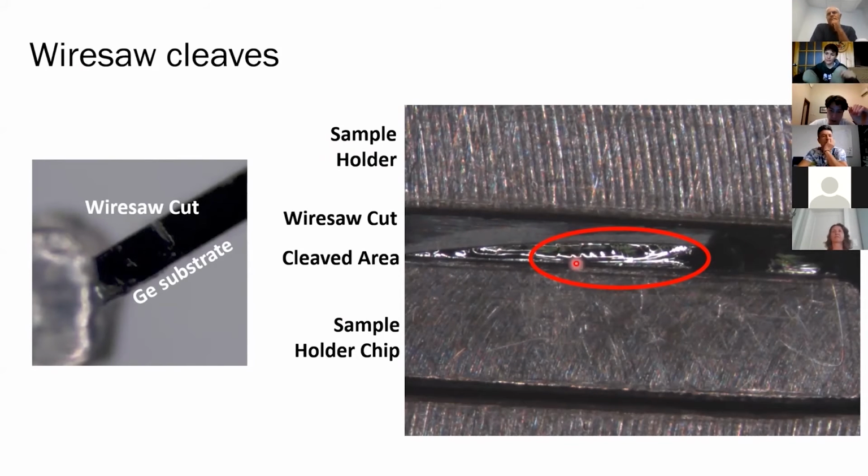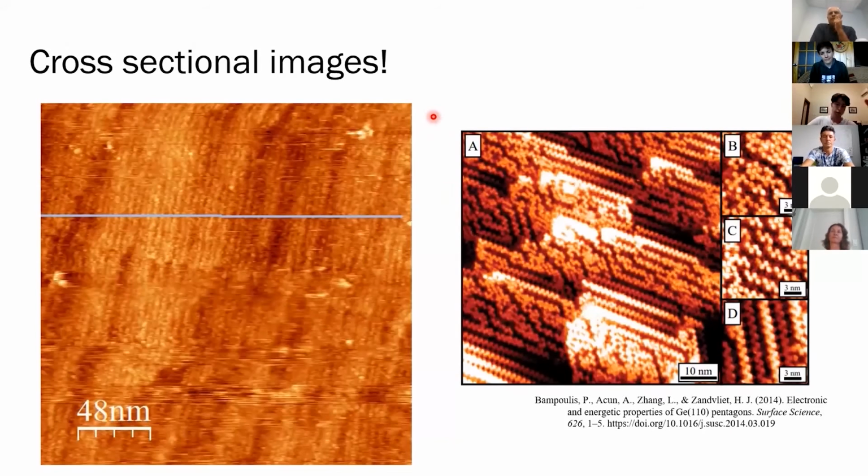there are these terraces almost, these steps, which is encouraging because if there are steps, it most likely points towards flat surfaces in between the steps. Now we don't know what it looks like atomically just from an optical picture, but we can hope that on the atomic scale, it cleaved somewhat similarly to how it cleaved under a microscope. We can also see at the edge maybe some steps and terraces, which is definitely encouraging. So I got one of these and cleaved it in situ in vacuum, and then imaged it